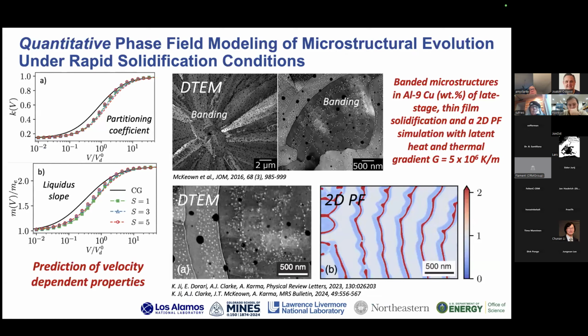And so one of the things that's challenging, I think, from the modeling point of view, is doing quantitative phase field modeling of microstructure evolution for rapid solidification conditions. So working with my colleague Alain Karma's group at Northeastern University, they've really been pushing forward in this area to be able to do phase field for rapid solidification. So this is an example where they're taking into account the prediction of velocity dependent properties, things like partitioning coefficient, the liquidus slope, and then we're directly comparing and validating that with our DTEM data.